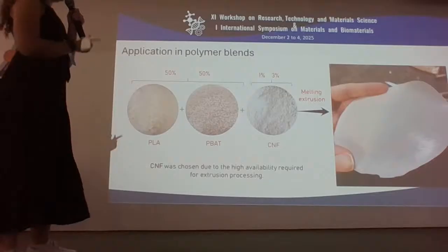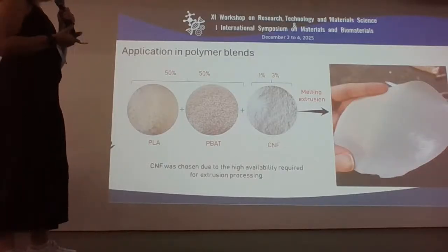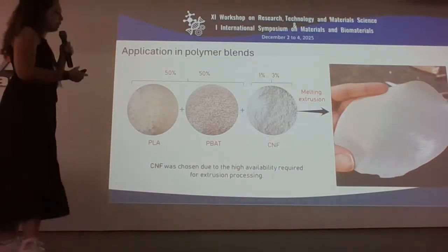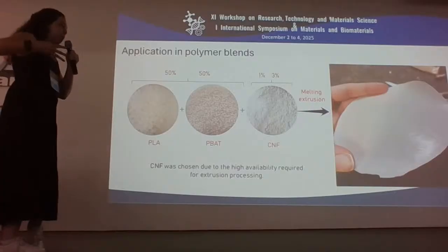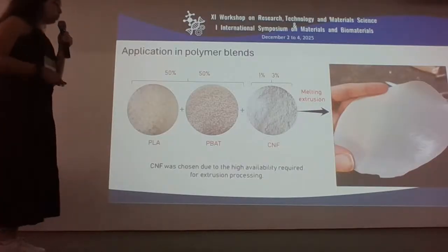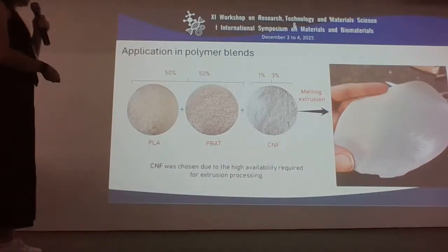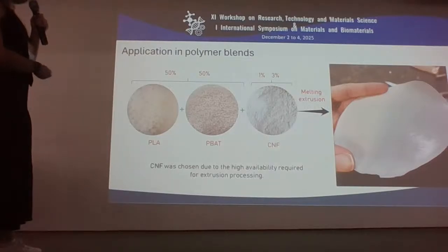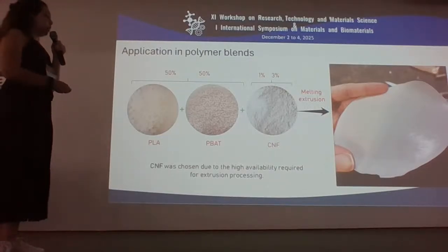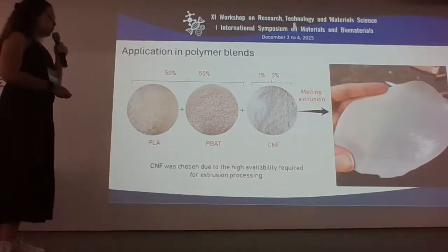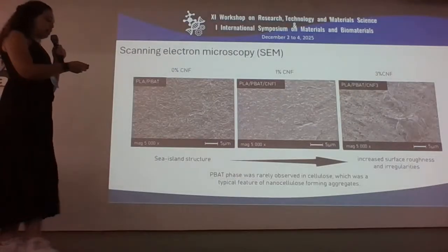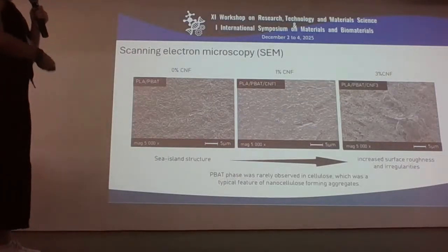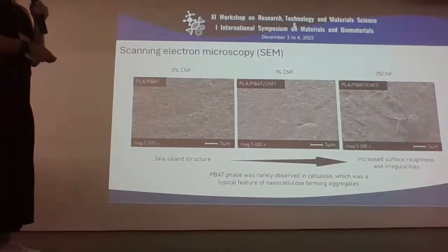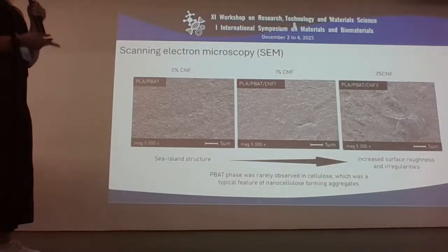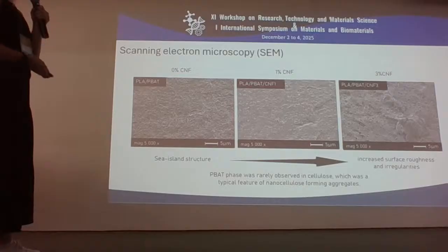And we use CNF to produce polymer nanocomposites. We use CNF because we have a large amount. For CNC we have just a smaller content. So we blended with PLA and PBAT, both biopolymers, and we varied 1 and 3% of CNF content. In this image, we can see that when we increase the CNF content, we have an increase in the roughness and some irregularities because of the CNF. This is common when we use CNF.